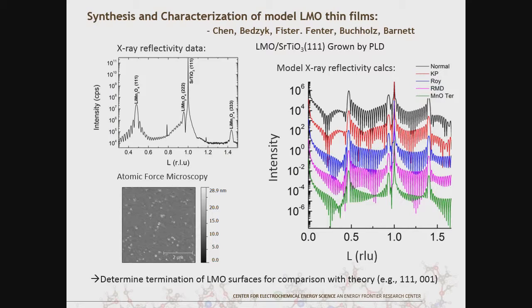The challenge here is to really get the high-level understanding of the electrode-electrolyte interface. One approach is to use X-ray reflectivity, which is my own specialty. This is work being done by Xiao Chen, a graduate student at Northwestern that we share with Mike Bedzyk. These are LMO films grown on strontium titanate, epitaxially grown.